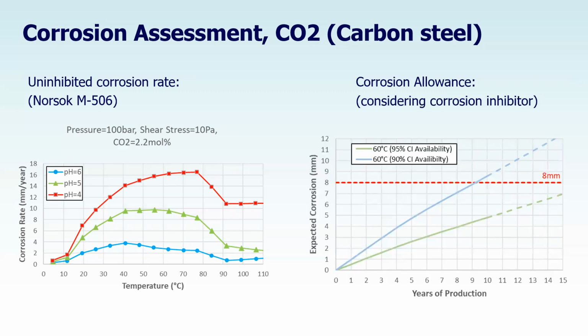As the next step, we calculated the corrosion allowance required if we inject inhibitor. You can see on the graph expected corrosion against years of service. The upper blue line shows 90% inhibitor availability, and the lower green one shows 95%. There is also a red 8 millimeter line, which serves as an indicator above which you may want to start considering CRA materials. As you can see here, 90% inhibitor availability will not really work in our case.